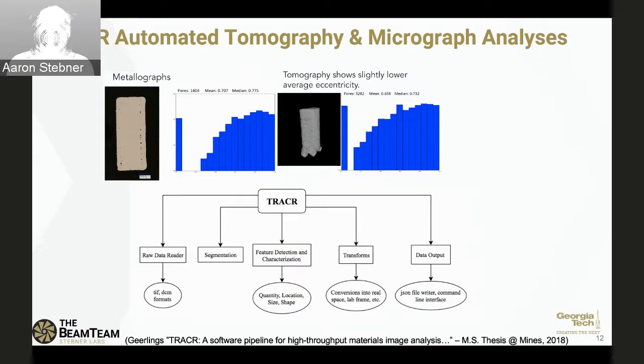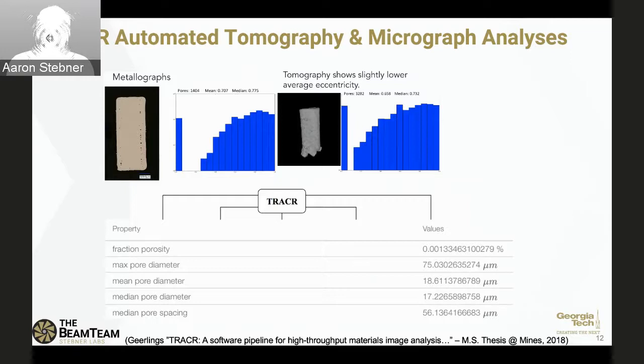So we developed in a master's thesis a data pipeline for doing this, and what you're seeing here is a comparison of serial sectioning microscopy versus the statistics in microcomputed tomography for the same sample. So we did a benchmarking there. If you click again, we could automatically populate a database with all of these calculated statistics about the porosity in each sample.